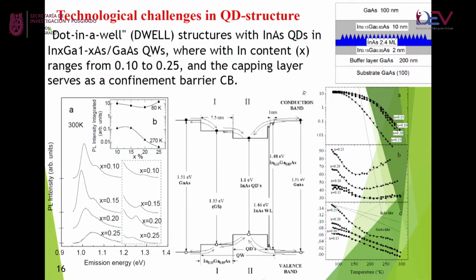You could see here that compositions, for example, 0.10 and 0.15 do not cause decreased intensity, but compositions 0.20 and 0.25 decreased the intensity of the quantum dots essentially. Here I show the energy diagram, and we created a theoretical model to explain this effect. This model is connected with the thermal escape of carriers from quantum dots, provoked by higher temperature, and due to this, the intensity of the quantum dots decreased.